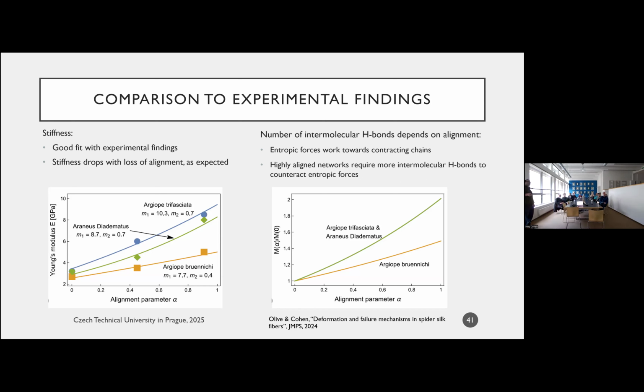So what you see here is the stiffness as a function of the alignment parameter, right? And this is the stiffness for a fiber that's super contracted. So if I have a fiber, I put it in water, I take it out, I let it dry without applying any force. I stretch it, I measure its stiffness. This is its stiffness. Keep in mind, in this state, the microstructure of the fiber is just randomly oriented. There's no orientation in the fiber itself, right? So it's randomly oriented, and that is why it's very soft, or relatively soft, right? Again, this is in gigapascals.